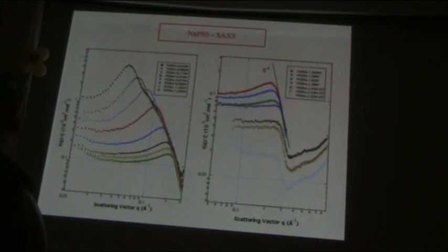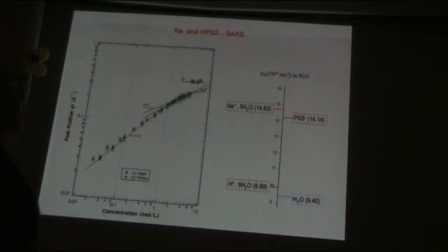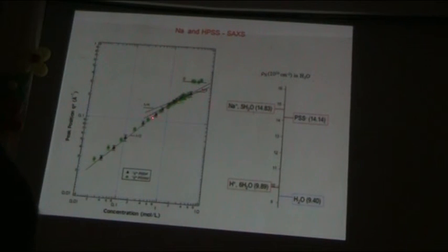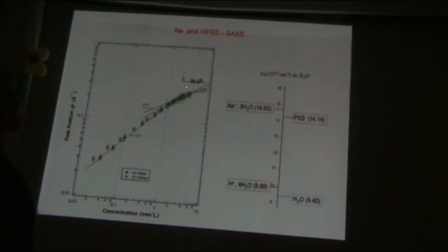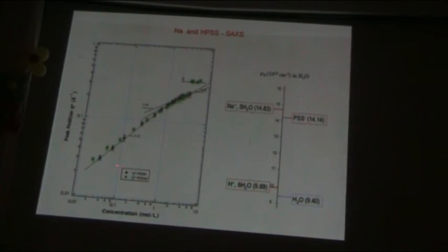At high concentration, you observe what Nishida has observed before. So you have some ionomer regime. I don't want to speak about that. So you observe C to the one-half, C to the one-fourth, and after something which is a pure ionomer regime, because you have decreased the dielectric constant of the solution, of course, and so you have dipoles here, and you have some association in between these things.